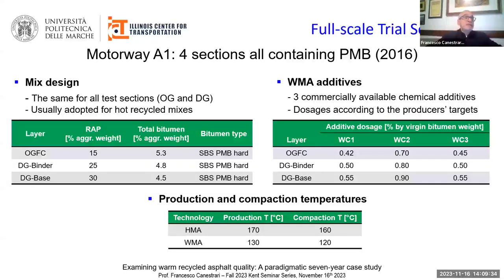The mixtures of all test sections were produced considering the mix design usually adopted for hot recycled mixtures. The open graded mixtures contain 15% RAP, the dense graded binder mixtures contain 25% RAP, and the dense graded base mixtures contain 30% RAP. In all cases, both the virgin bitumen and the bitumen from RAP are SBS polymer modified with 3.8% SBS polymer by binder weight. All hot mixtures were produced at 170 and compacted at 160 degrees C, whereas all warm mixtures were produced at 130 and compacted at 120 degrees C.